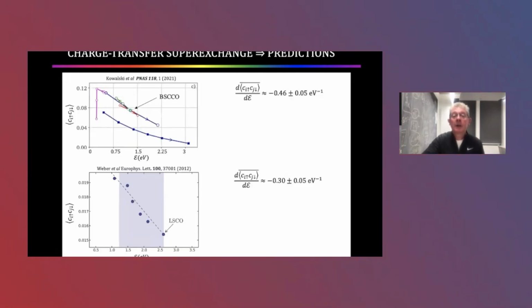All right. Now in order for us to make an experimental test, we needed to normalize the value of the amplitude of the pair wave function. So we normalized it by the value reported by the theorists for the standard materials parameters of the compound, the charge transfer energy which actually exists in the real compound. So that allows us to look at their predictions and say, in BSCCO, the pair wave function amplitude goes as minus 0.5 per electron volt of charge transfer energy. And for LSCO, it goes as minus 0.3 per electron volt.